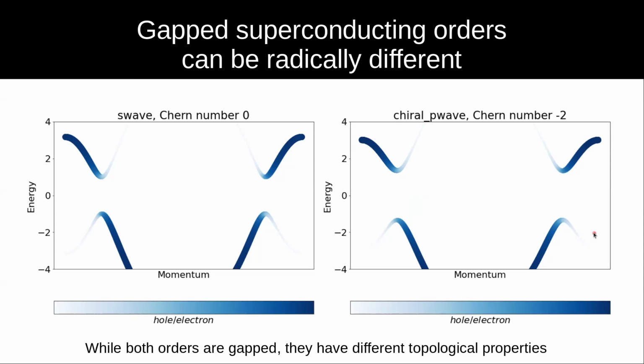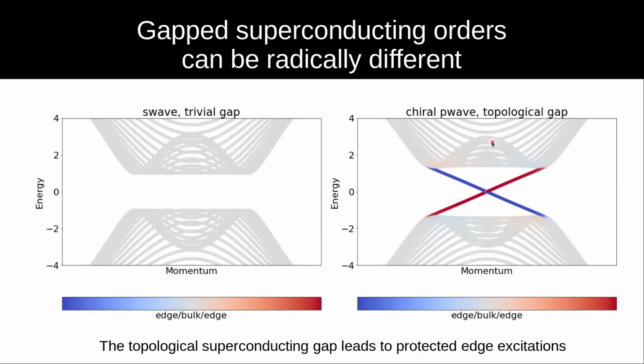They are indistinguishable. But if you look at their topological properties, if you look at the Chern number associated with these superconducting states, then you see that they are completely different. The S-wave superconducting state has Chern number 0, whereas the chiral p-wave state has Chern number -2 or +2, depending on the chirality. And of course, this has a massive consequence when you think about a finite system. So in the case of an S-wave superconducting order, you effectively have a gap everywhere, both in the bulk and at the edge of the system. Whereas if you look at the spectra of a chiral topological p-wave superconductor, you see that you have a gap in the bulk, but then you have gapless edge states at the edges, one that propagates in one direction and the other that propagates in the other direction. These edge states will become propagating Majorana modes. These modes are fractions of an electron, and this is what we are going to address later on.